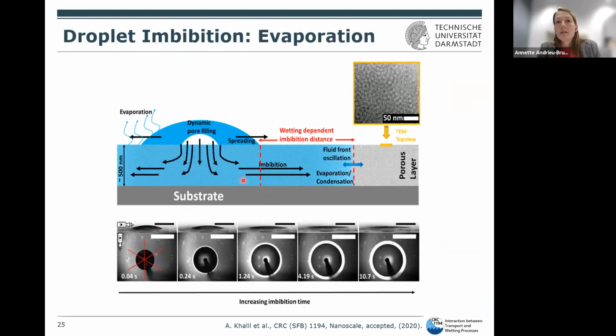So what then happens if you deposit a droplet, and this is again very interesting on how fluid imbibition in these pores actually occurs, is that you see the formation of a so-called imbibition ring. So what is done here is you deposit a droplet, and what happens, I will show this in the video, is that this ring is forming, and now you can analyze the width of this ring and relate this to models of fluid imbibition in such materials.